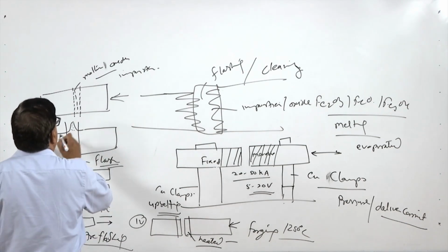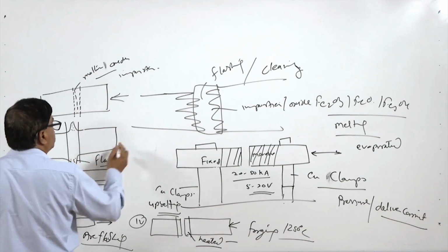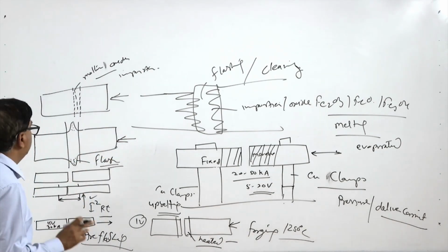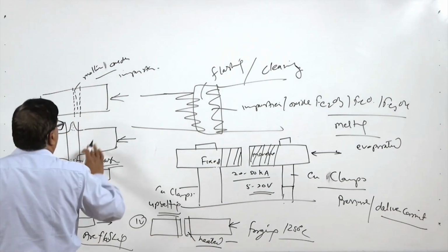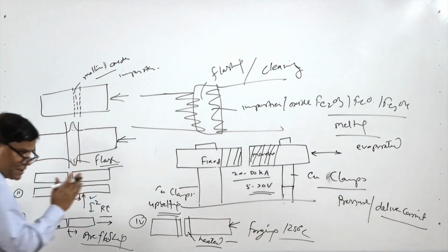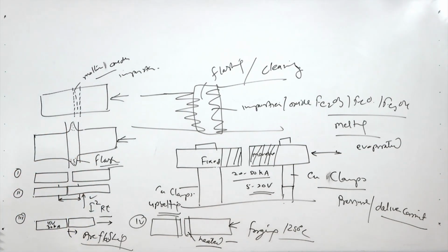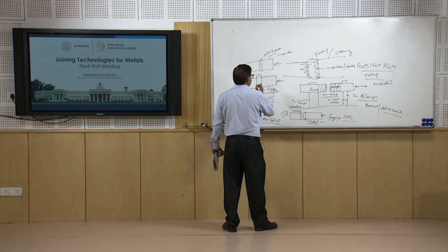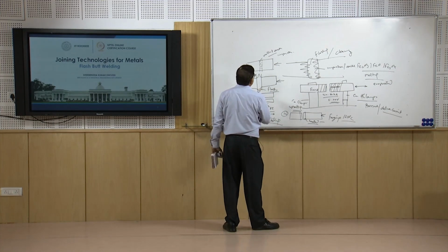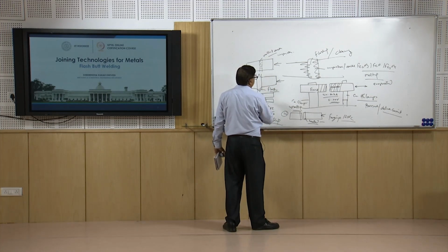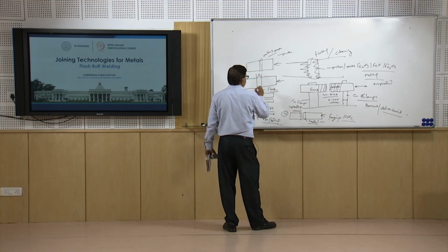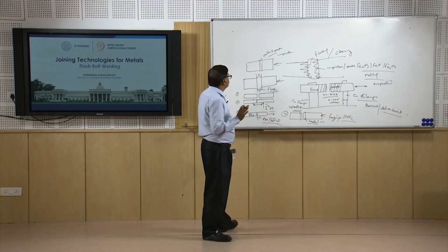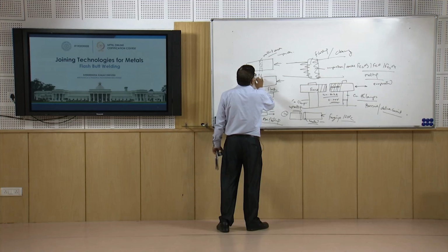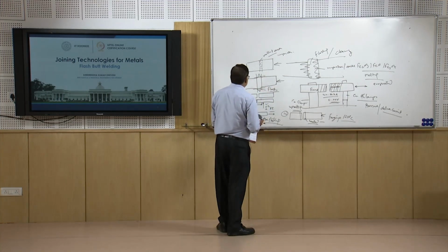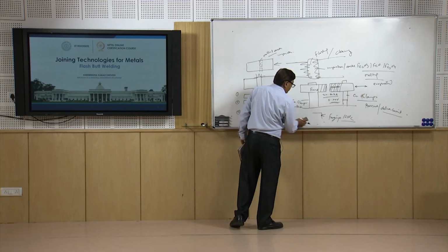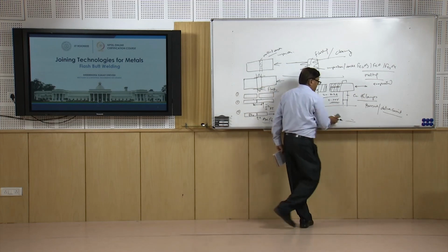Once the joint is formed, and this upsetting basically happens under the forging conditions, the metal near the ends becomes soft. So, under the forged conditions it gets upset, while the locations away from the interface remain at lower temperatures, so they do not experience any change in dimensions or upsetting. So, this is how the joint is formed. Impurities will automatically be localized here under the optimal set of pressure and temperature conditions, and the flash is subsequently removed through post treatment or post machining operation for achieving the required size and shape.